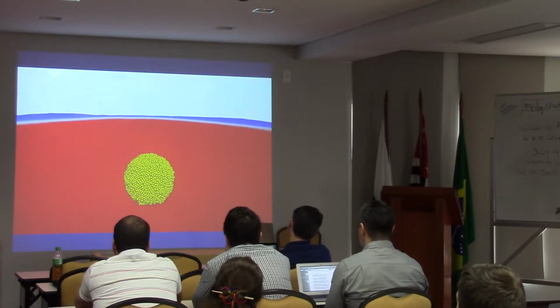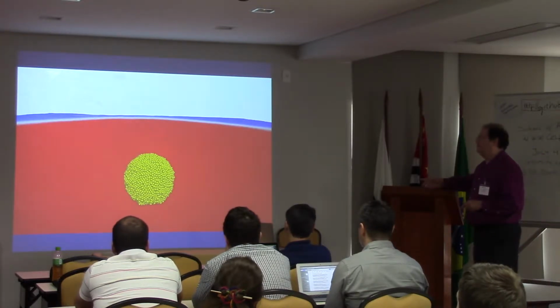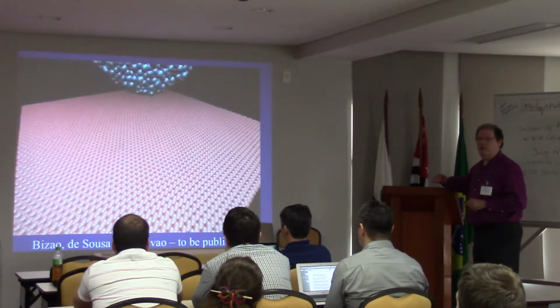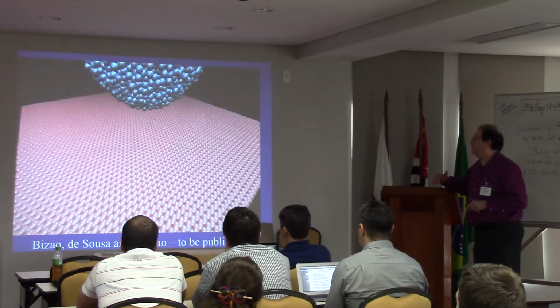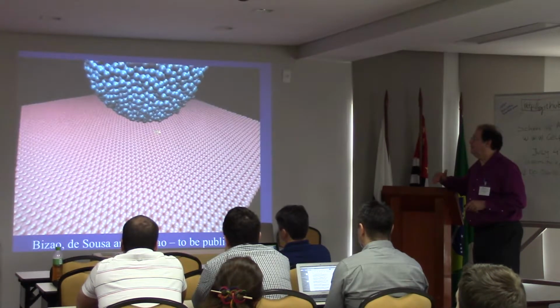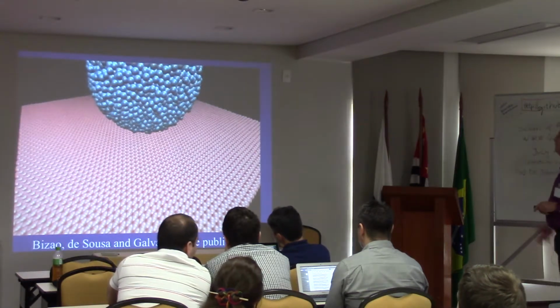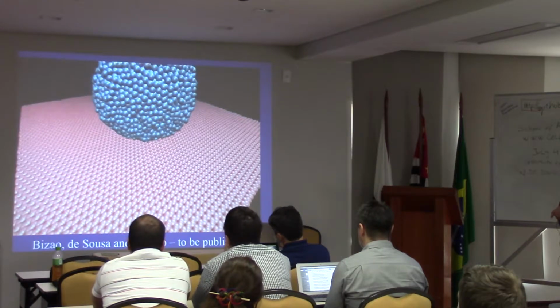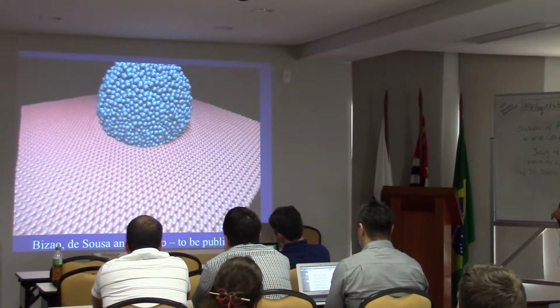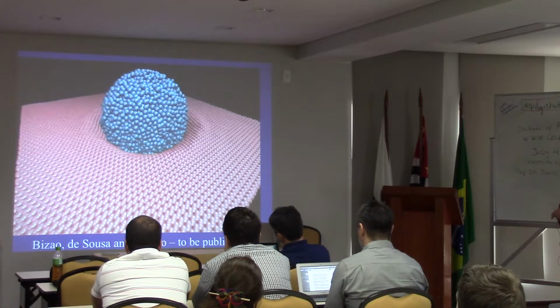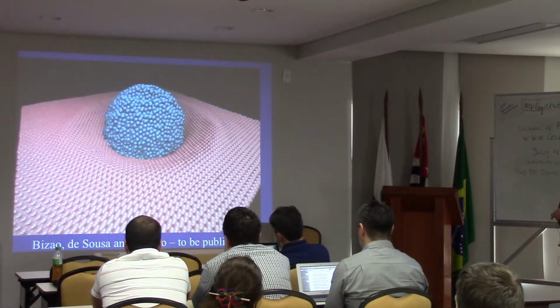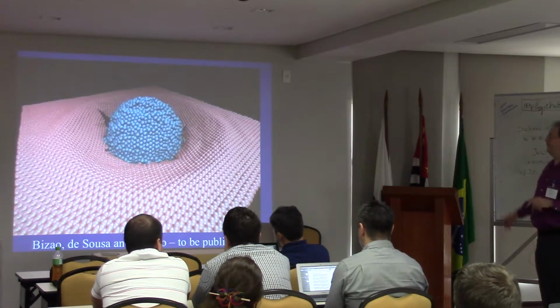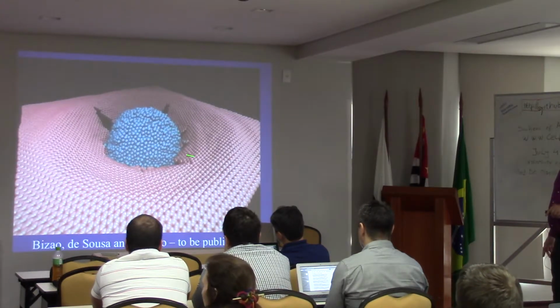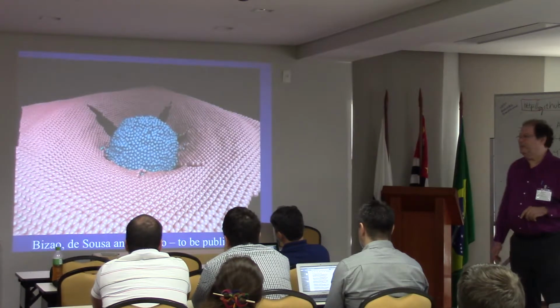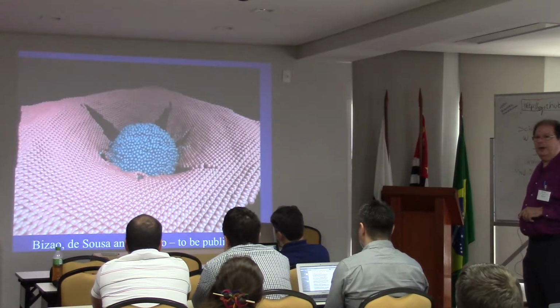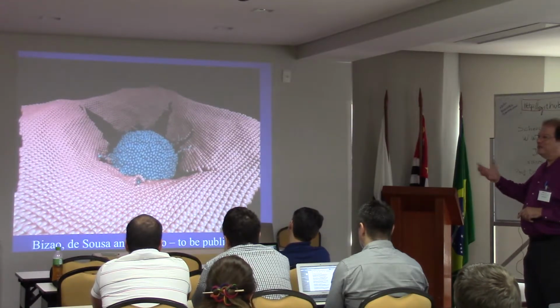Okay. Then go to the second part, the really important part. How does it break? Then we shoot again. This is very slow motion, the simulation, so we can follow the deformation. This is a nickel particle shooting at very high velocity, in the same range as the experimental one, and we slow it down to see how it breaks. It starts deforming up to the limit, then starts breaking bonds. The graphene sheet is suspended at the edge. You see? The petals appear, and the angles are exactly the same as in the experiments. It's amazing how well this reactive force field for carbon works. This is almost an experimental tool for these structures.